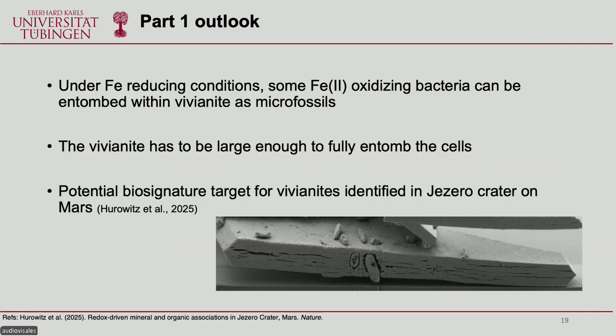And so to summarize part one, we've shown that under iron-reducing conditions, we think that some iron oxidizing bacteria can be entombed within vivianite as microfossils. And since we've done this for a few vivianite crystals, the size of the vivianite crystals really matters as well. It cannot be something small. It has to be big enough to fully entomb the cells, which means that we can tell apart some of the environmental conditions that this might happen in as well. And this is very interesting because vivianite has only recently been identified in Jezero crater on Mars. So if we can get those vivianite nodules back to Earth, and then we apply the same techniques, maybe we can find these microfossils there as well.